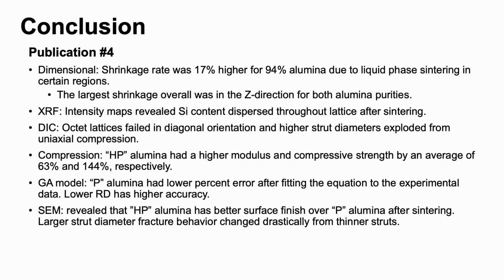Using the DIC analysis, we saw that the octet lattice structures failed in a diagonal orientation, and when we used a higher strut diameter, essentially they exploded from uniaxial compression. From the compression test results, we saw that the high purity alumina had a higher modulus and compressive strength by an average of 63% and 144% respectively. When we used the Gibson-Ashby model, we saw that the P alumina lattices had a lower percent error after fitting the equation to the experimental data.